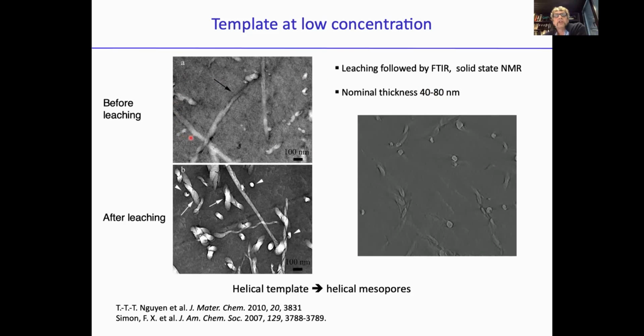And you can see that before leaching, this is the resin, and you can see that we have these objects that are included. You can see because they have different contrast. And when we leach them, of course, the contrast increases because we have white pores. It's white because there's no more material surrounded by the resin here. And when doing so, you can see here that we have the helical tapes I was talking about a few minutes ago. So these are the helical tapes, and we did a tomographic reconstruction here.